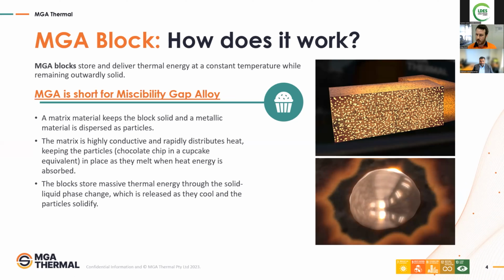Now, within that matrix, we have distributed grains of a phase change material, typically a metal, which in operation melts and freezes repeatedly, storing latent heat. And that's our primary energy storage mechanism. So the idea behind that is that we achieved the high energy density of the latent heat material without having the complexity of handling a material when it's a solid and a liquid. Macroscopically, they're always solid blocks because it's small individual discrete grains that are melting and freezing rather than the bulk of the material.